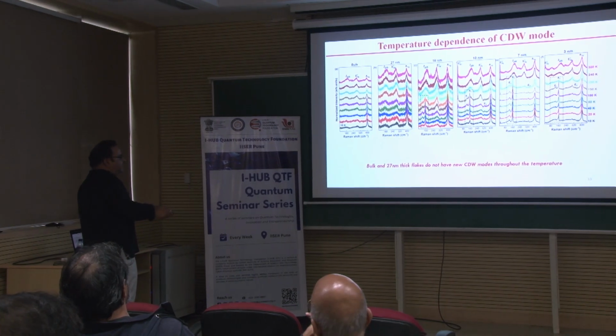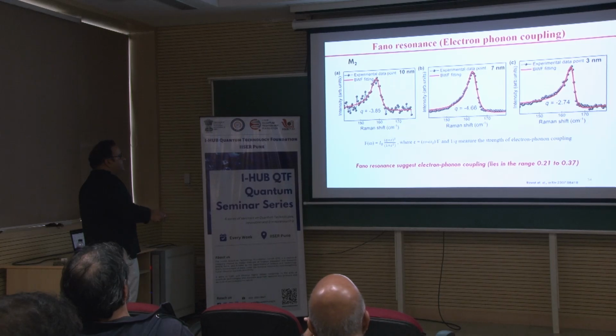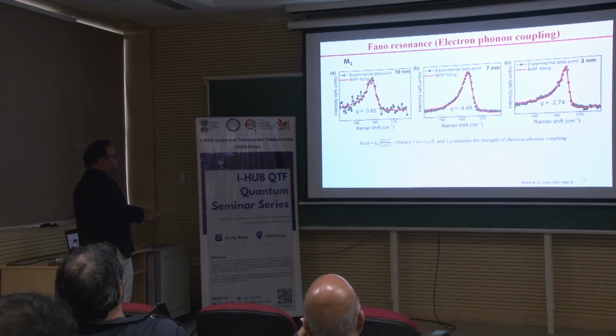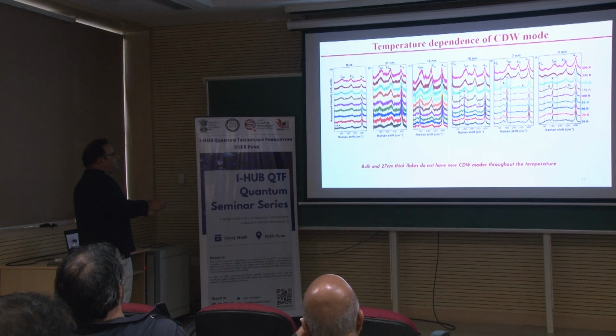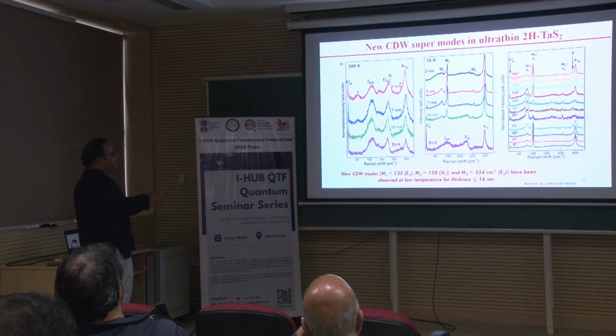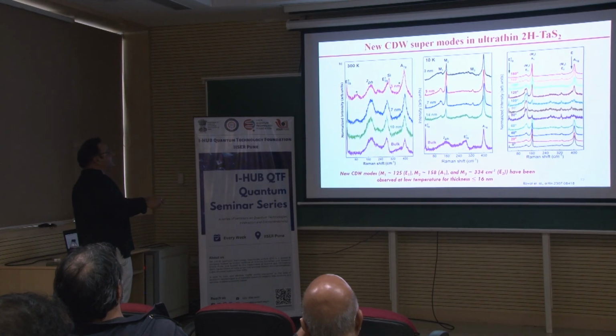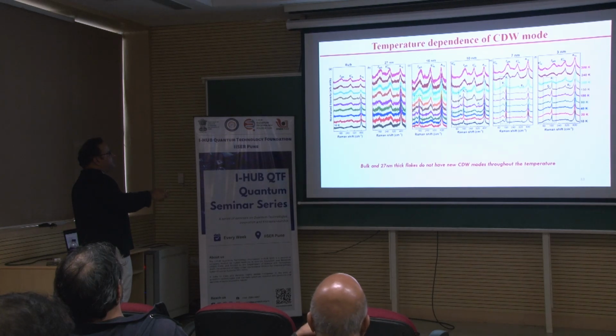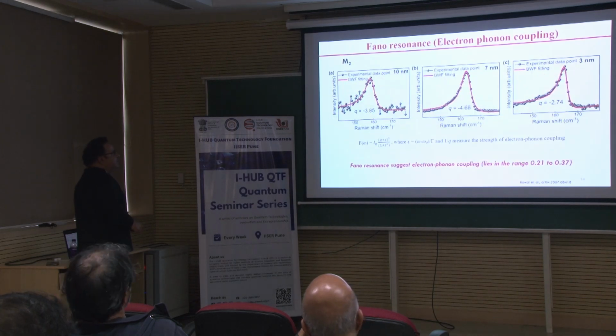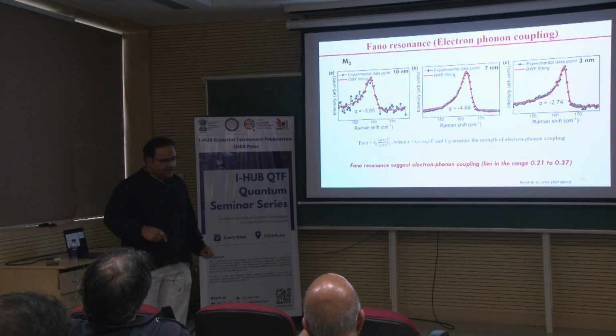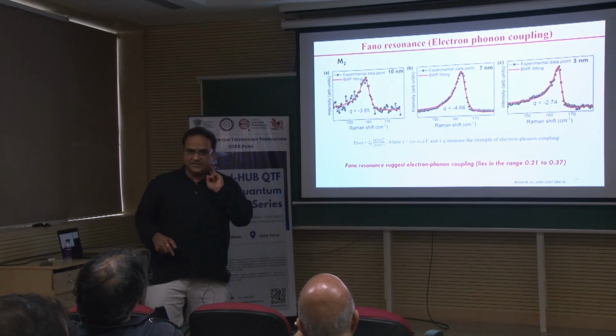The higher thickness does not have anything above 16 nanometer. We have data in between as well, but we have not shown it here. So, anything above 16 nanometer, you do not have these new modes which are coming because of the dimensionality, and we try to understand the fitting of the M2 mode, which is very interesting.